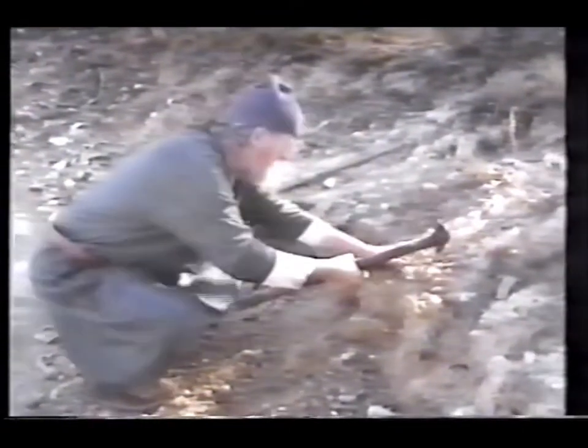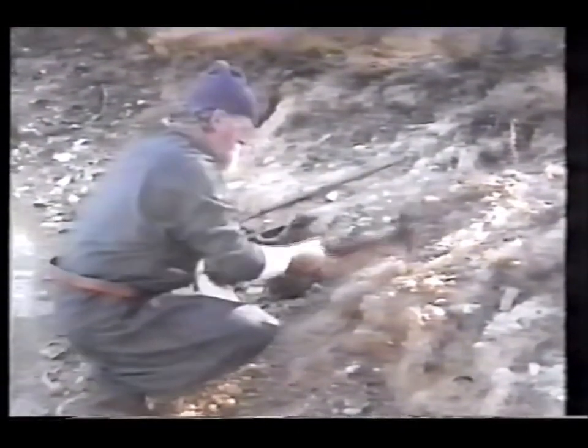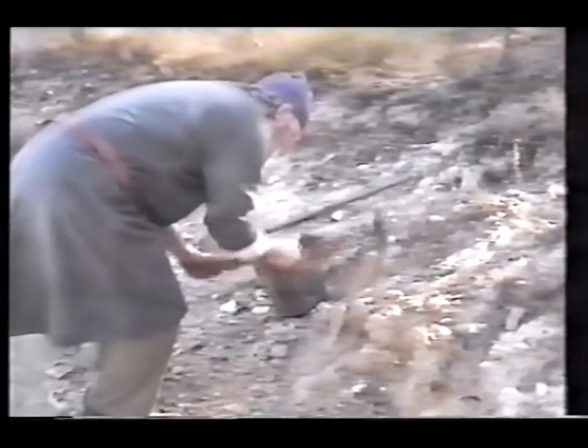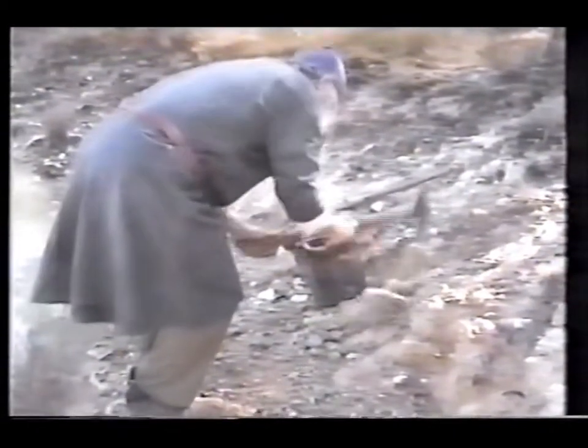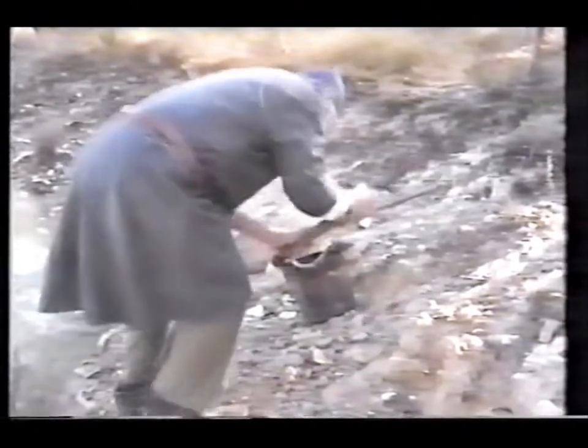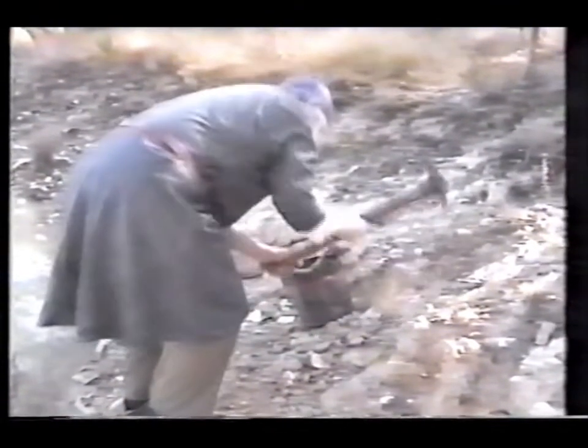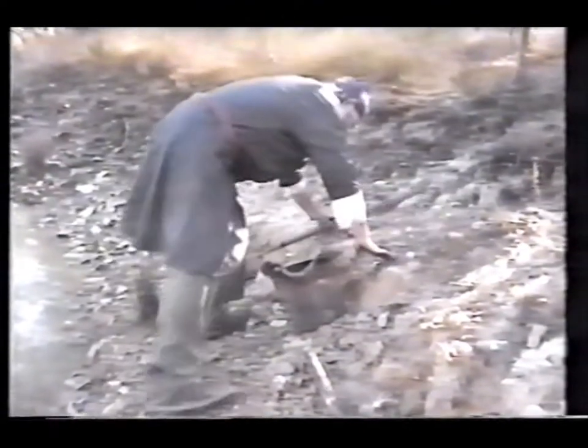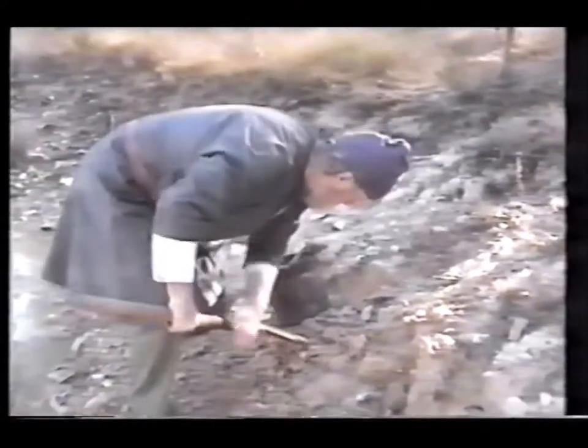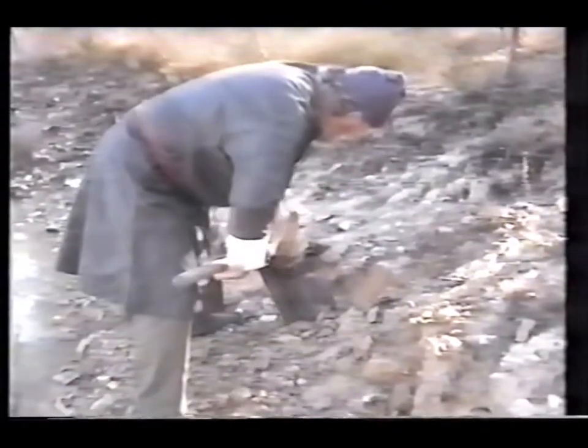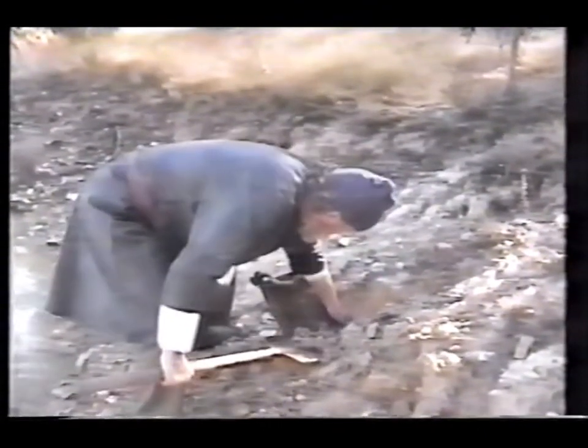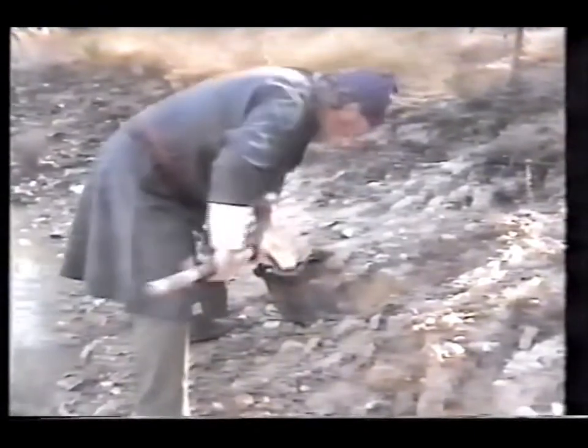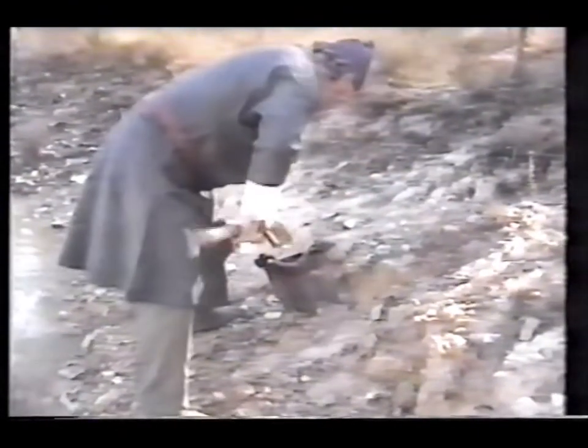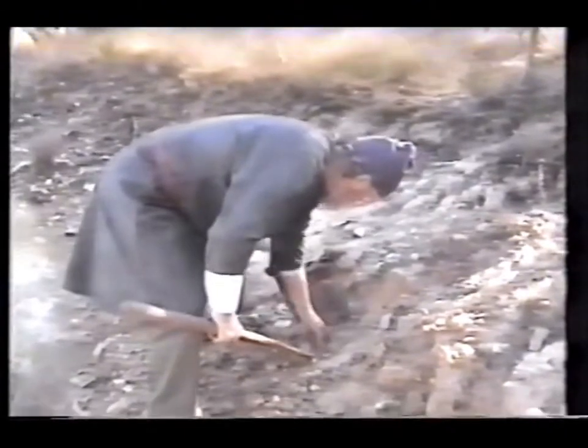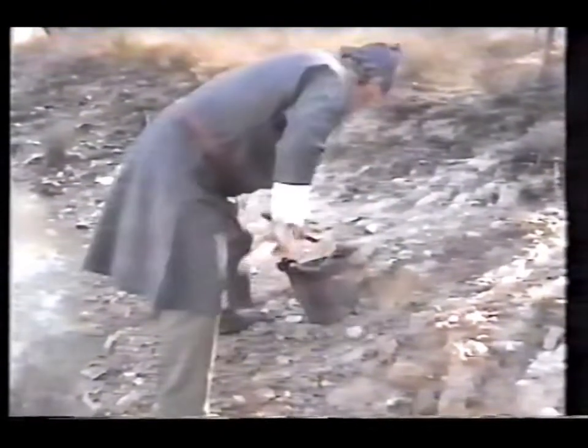The next job to be done, of course, would be making the furnace. For this, a clay would be required, preferably a refractory clay to withstand the high temperatures. Whatever clay was available was usually pressed into service. A rough rule of thumb would be that the whiter the clay, the more refractory it would tend to be. These clays would usually be excavated from river banks, possibly in a wet state, sometimes dry and then puddled up to the right consistency. The technique varied. The end result was much the same.